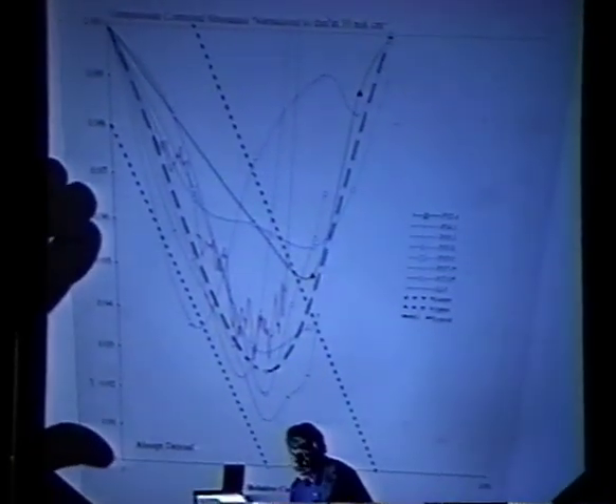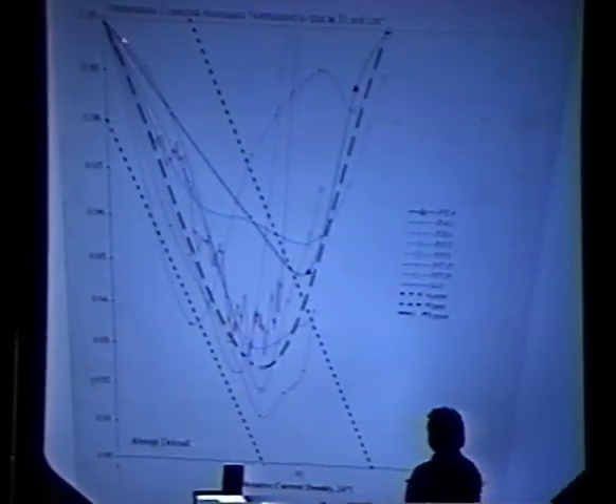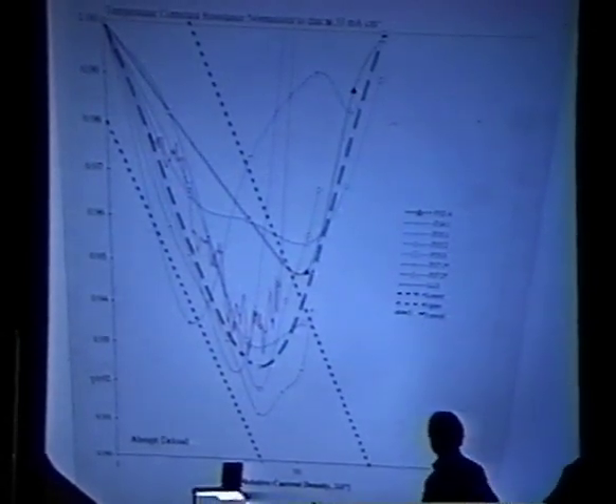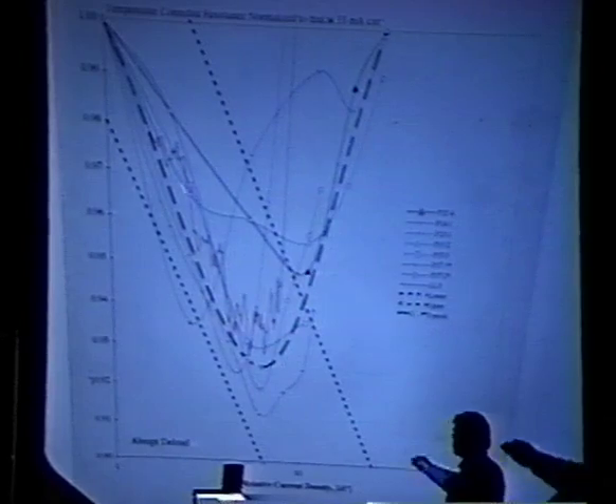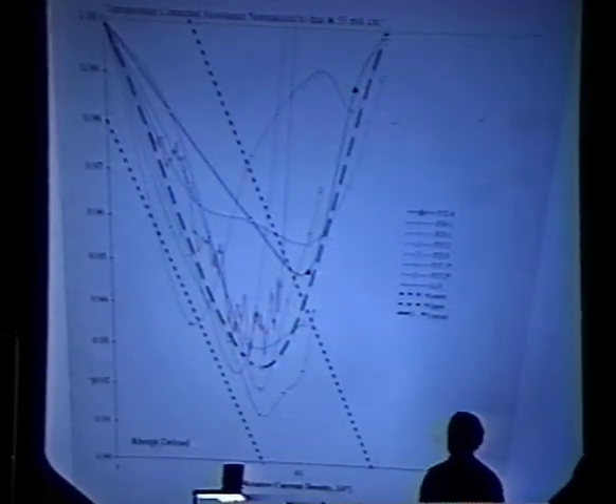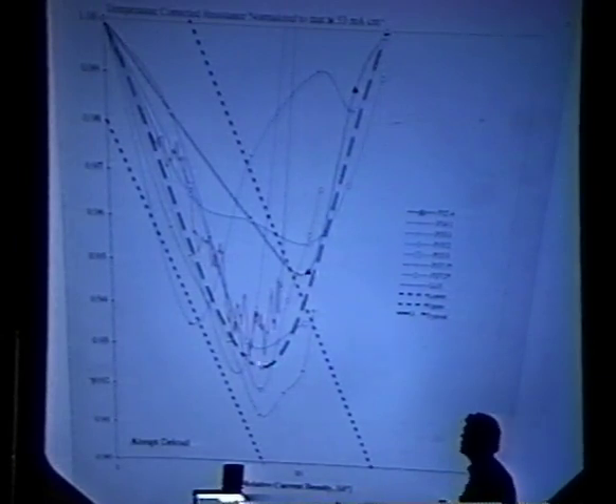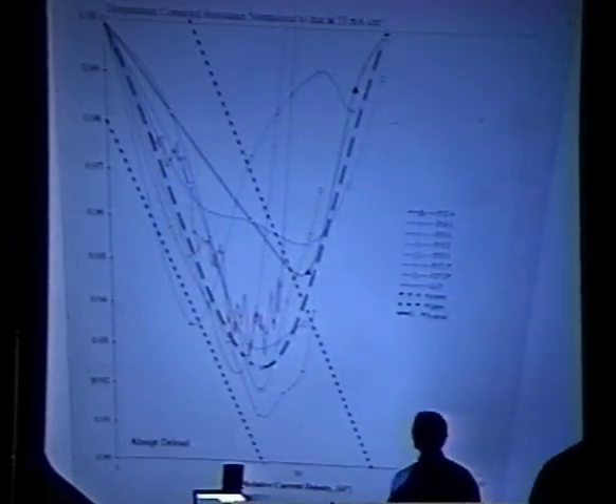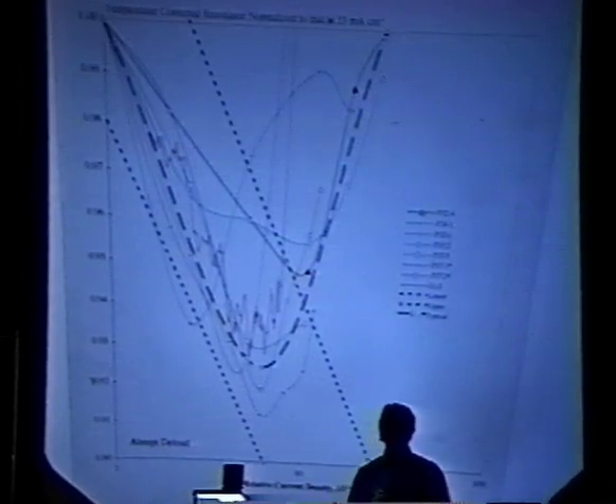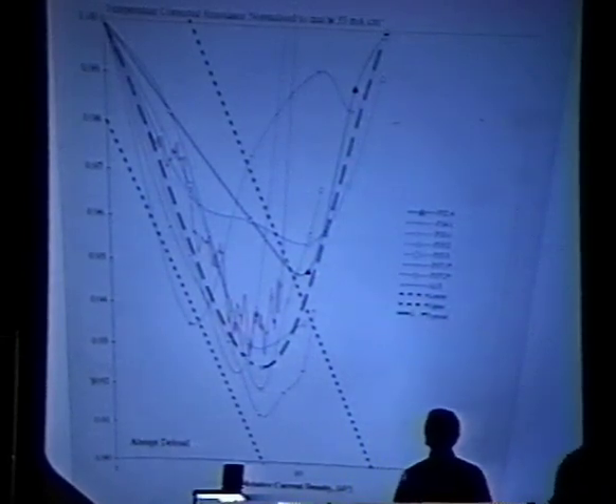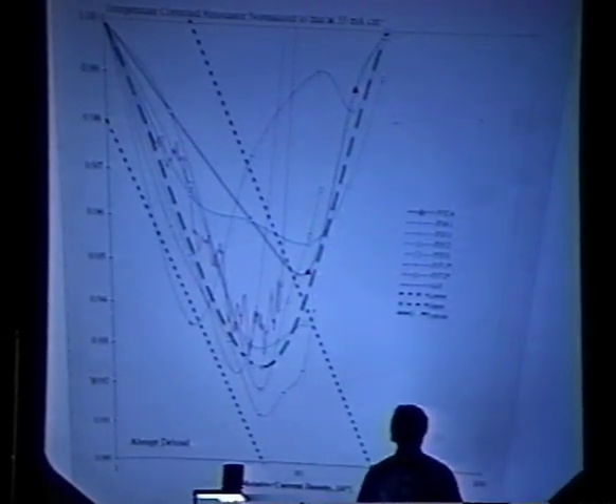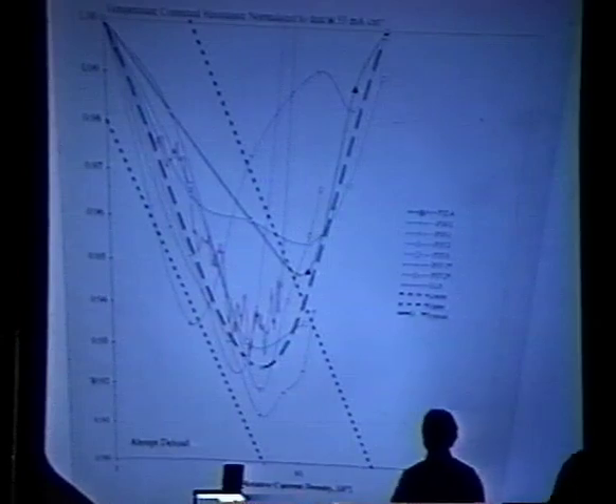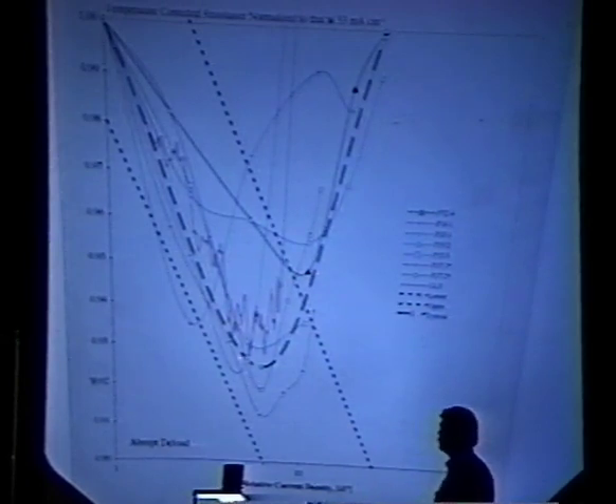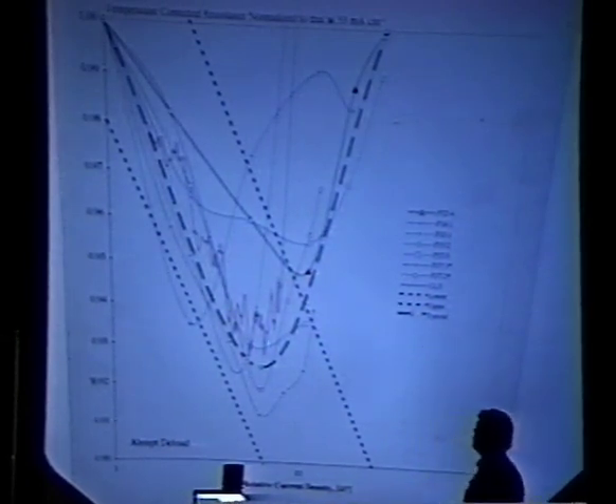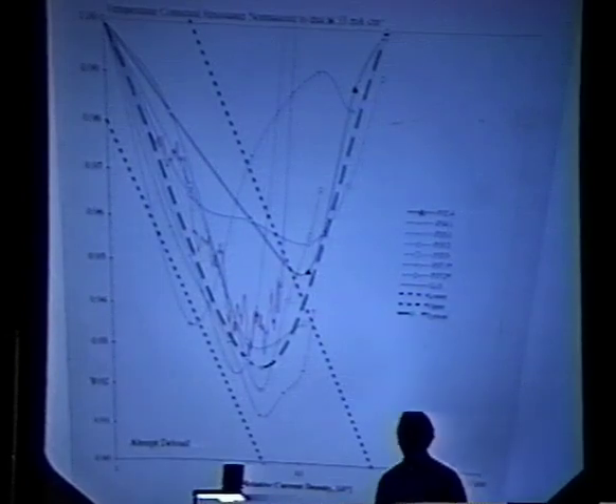Mode B behavior really starts out the same. Follows this, these are the same hatched lines that I had on the last curve. If it comes down, everything is doing very, very well. The cathode is loading well, and at some point it says, whoops, and they deload, precipitously deload, and never reload again. So there is a mechanism which, once you've embarked upon the trajectory that you desire to follow, an abrupt failure occurs which prevents the cathode from loading any further, and worse, it causes a rapid deloading towards the equilibrium loading condition.